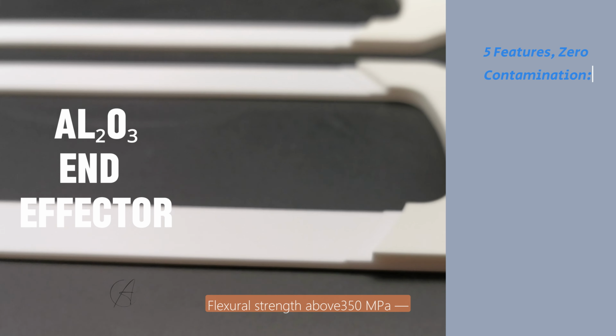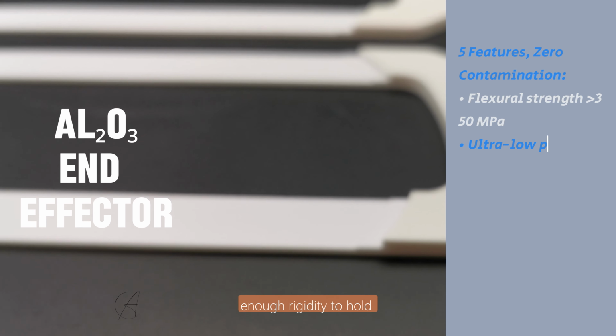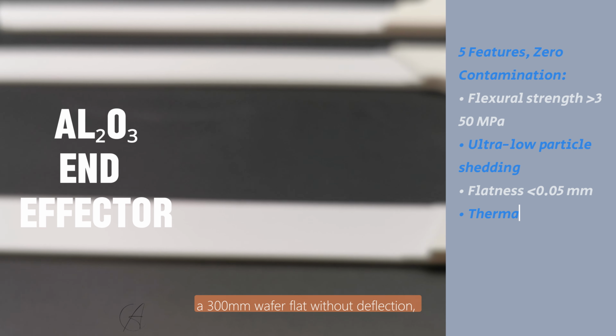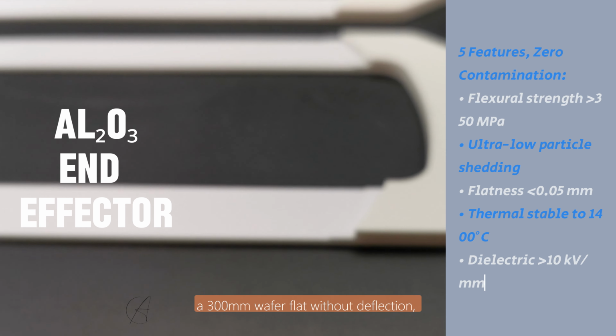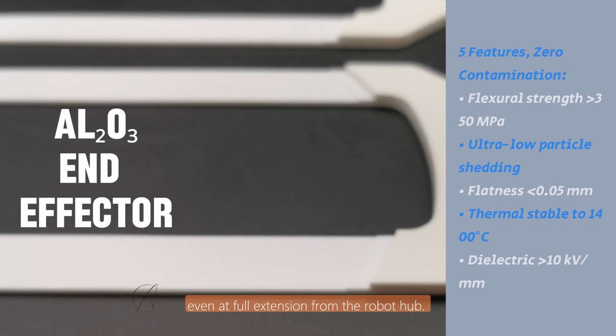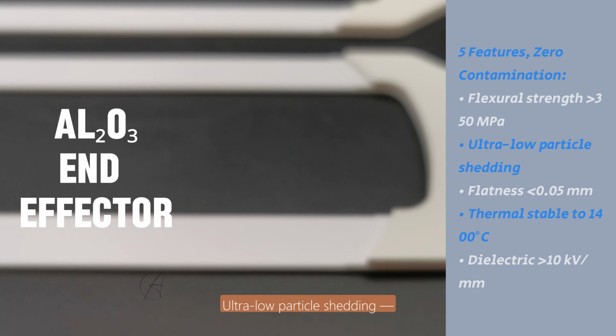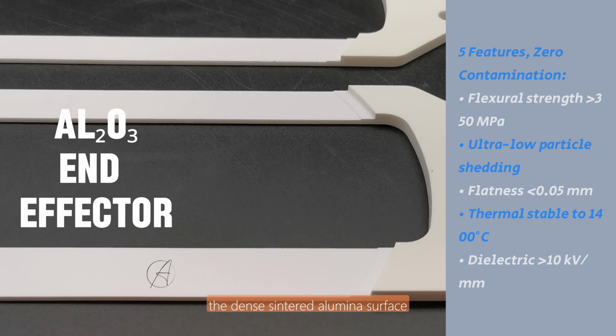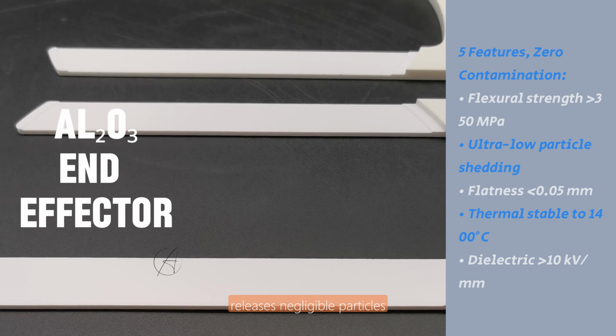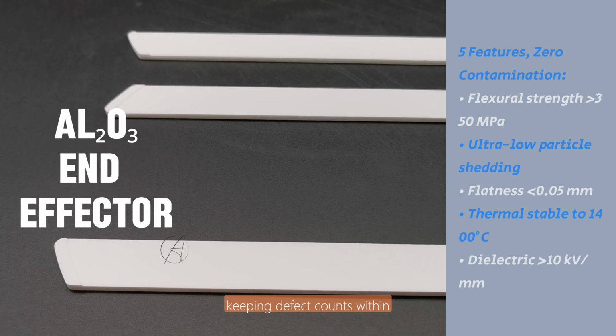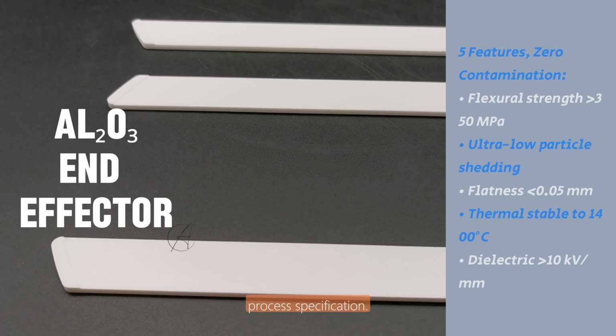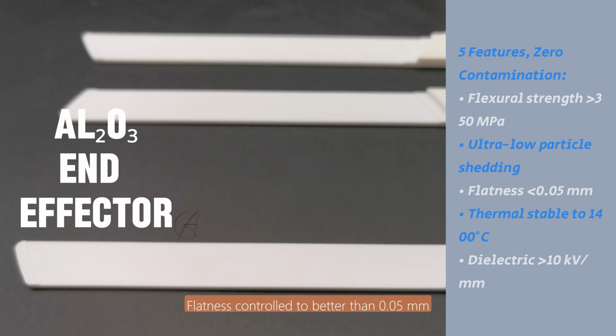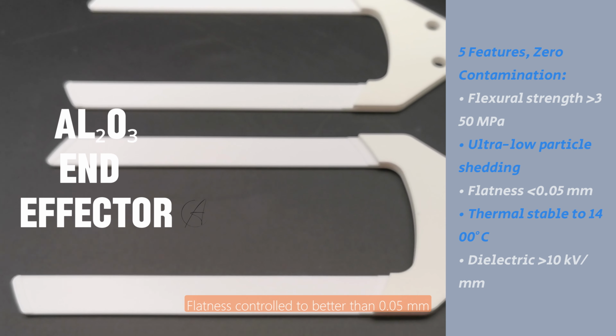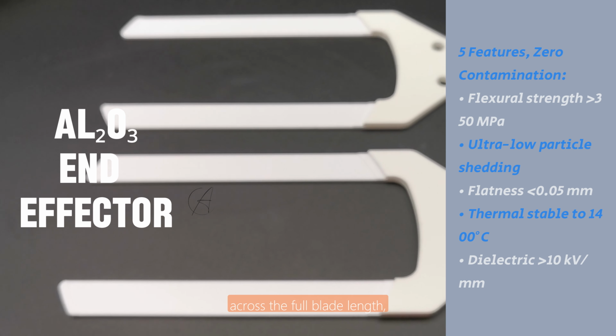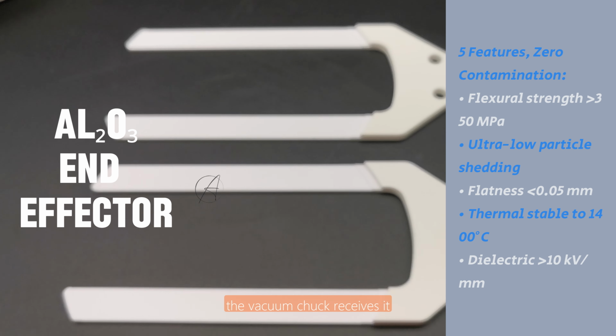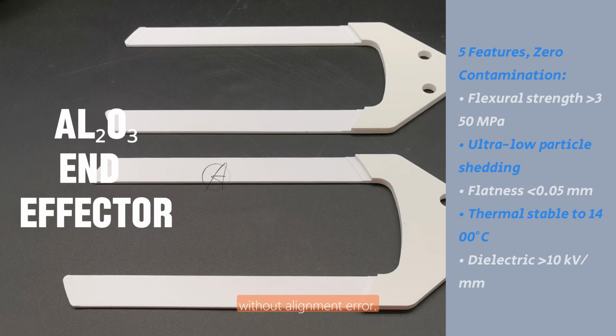Flexural strength above 350 megapascals, enough rigidity to hold a 300 mm wafer flat without deflection, even at full extension from the robot hub. Ultra-low particle shedding. The dense sintered alumina surface releases negligible particles during wafer contact, keeping defect counts within process specification. Flatness controlled to better than 0.05 mm across the full blade length, so the wafer sits level and the vacuum chuck receives it without alignment error.